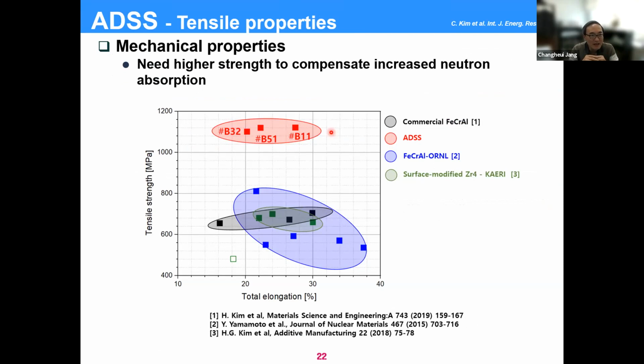So the idea is to compensate those absorption cross-section differences, you have to make the cladding thickness decrease from the current 0.5 millimeter to 0.3 or 0.35 millimeters. But if you want to decrease the thickness, you have to increase the strength of the material, okay? And it should also have a certain ductility. So this is the reason why we favor a high strength material that also has a certain amount of ductility. So the thickness becomes smaller, and you can have a little bit bigger fuel pellet within those cladding materials.